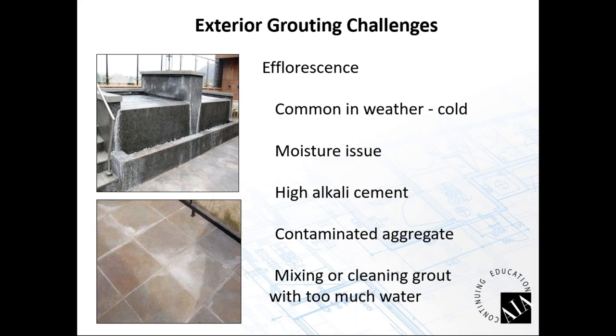Also being sure that if you're using a true mortar bed, that you're not using a contaminated aggregate. I've been on jobs where they swore up and down they got the right mortars and coats, but the sand that they were using was not a clean sand. And after thorough testing, they found that the efflorescence was based off the sand not being a clean washed sand. So making sure these are all taken into consideration when you're doing an exterior application.